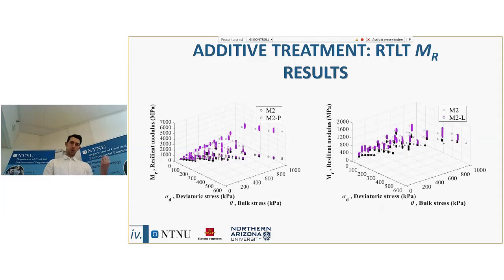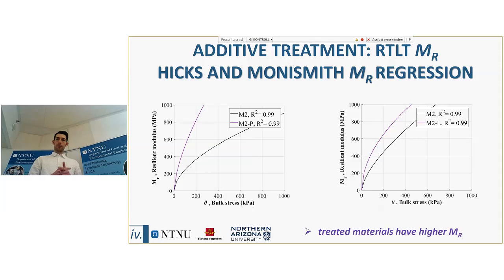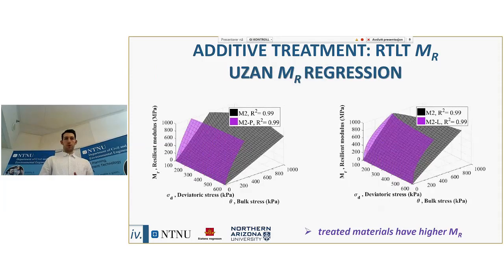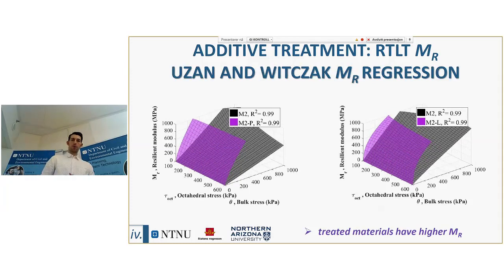And again, we can also plot these results in a 3D plot. Again, the magenta colors, the resilient moduli corresponding to the treated materials, are higher than the resilient moduli connected to the untreated materials. As mentioned before, first we followed the Hicks and Monismith regression. Then we also displayed the results according to the Uzan model regression. Whether you're talking about a surface like in the Uzan model, or a line like in the Hicks and Monismith model, it's always possible to see that the magenta color, the treated material, performs better than the untreated material.